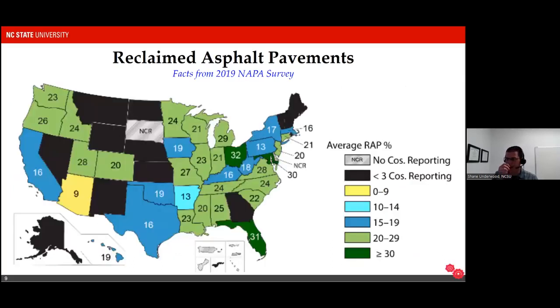The map on this slide is basically meant to show you the typical usage rates in the US. So where I live, North Carolina, our average RAP usage rate is 24%. But this is the average rate. There are surface asphalt mixes that use up to about 40% RAP in some cases, and these have been used successfully. Some of the engineering behaviors are more challenging, but there are experiences that use very high RAP dosages.